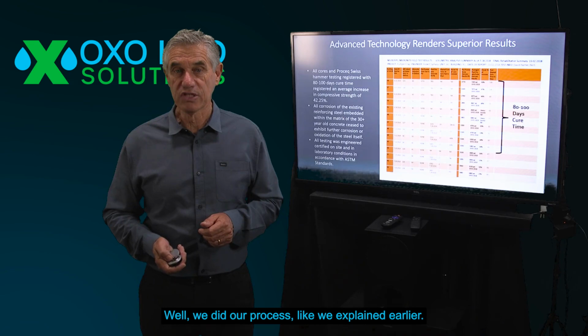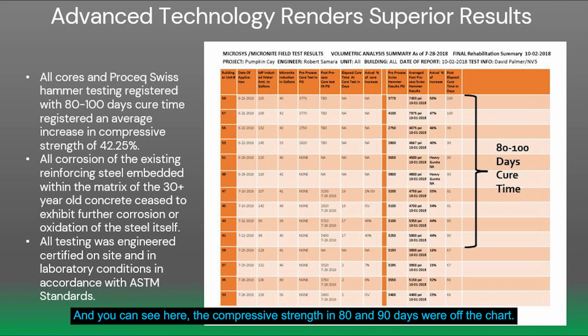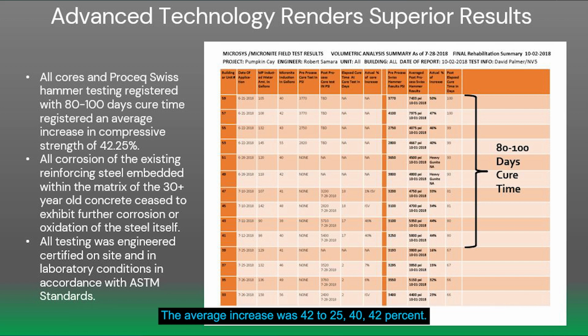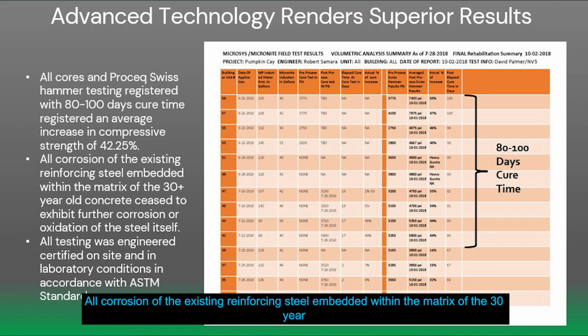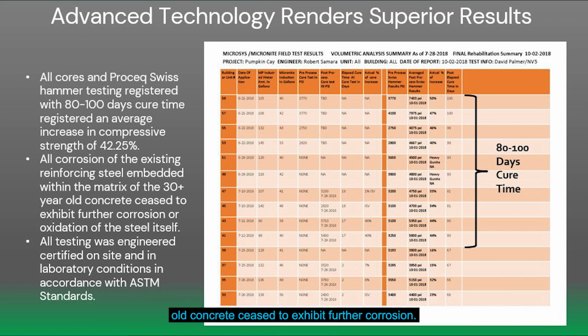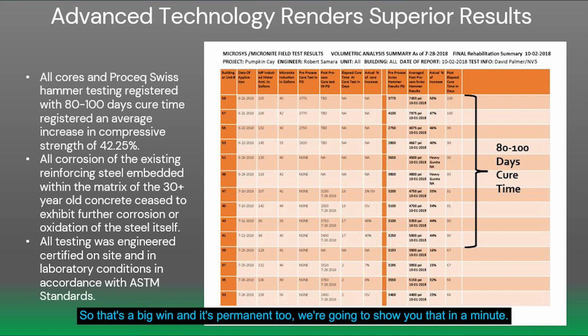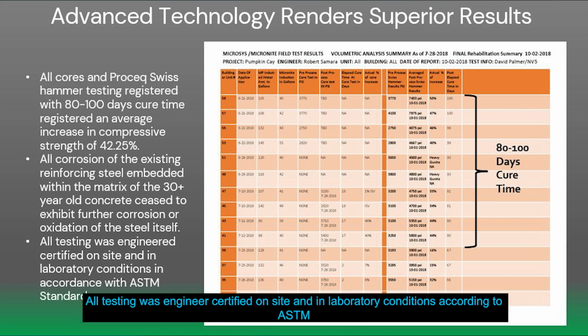So what did we do to fix that? Well, we did our process like we explained earlier, and you can see here the compressive strengths in 80 and 90 days were off the chart. The average increase was 42%. All corrosion of the existing reinforcing steel embedded within the matrix of the 30-year-old concrete ceased to exhibit further corrosion. So not only does this stop it, it keeps it from rusting anymore. So that's a big win, and it's permanent too. We're going to show you that in a minute.